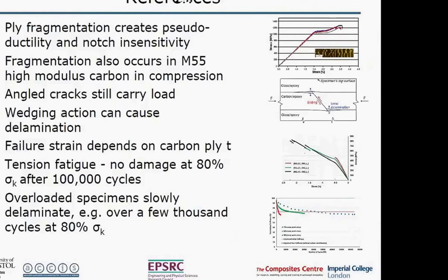If you change the loading rate, then you change the rate at which they shear, and in some cases you can reduce the pseudo-ductility. You need to tailor it to the particular matrix, and because it varies with strain rate and indeed with temperature, you've got a problem of optimizing for a particular condition and then looking at what happens off that condition. So it opens up a whole lot of new issues in terms of how you optimize the material response to get the response you like.